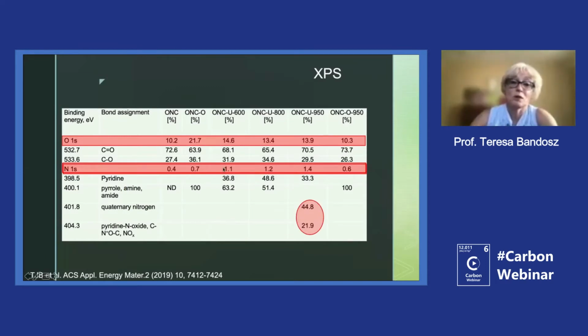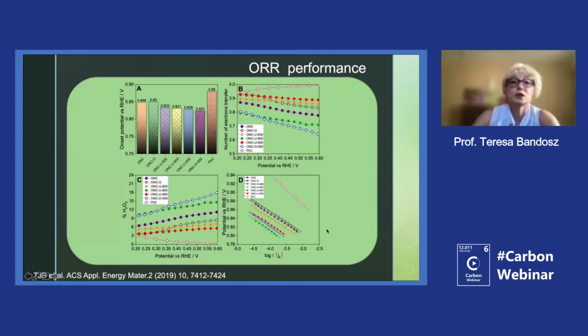We introduce a little bit, so it is seen here. And by changing the temperature, we also change the chemistry of nitrogen. Of course, we had the pyridinic groups, which were important, but in this case, in the case of this carbon, we have also the quaternary nitrogen on the surface. And here are the results again. So again, the best carbons from the viewpoint of the onset potential were those without nitrogen.